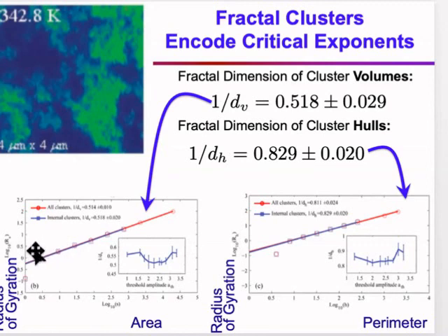And you see that there are several points here that are lying on a line. A line on this plot, of course, is power law behavior. And with about 2.5 decades of scaling here, perhaps 3 if you include that point, I'm pretty confident that we can extract that critical exponent, okay?